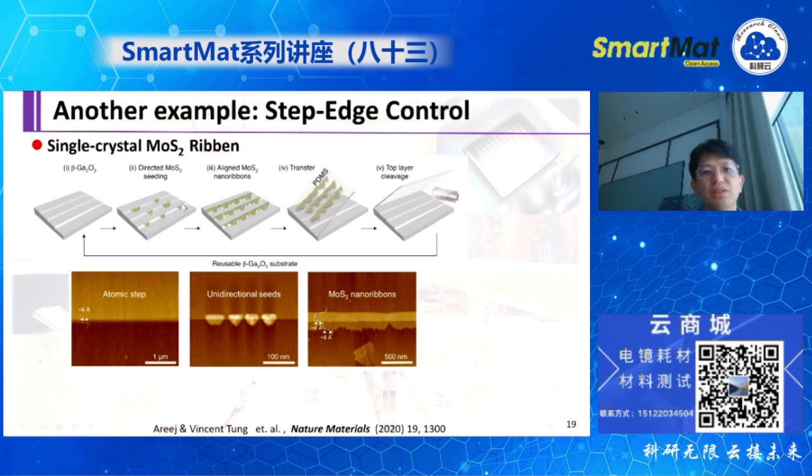And then due to the surface structure differences, the precursor diffusion direction is limited. I mean, along the step edge direction, the diffusion rate is faster. So vertical to this step edge direction, the diffusion rate is very slow. So therefore, it actually forms, I'll say, ribbon structures.